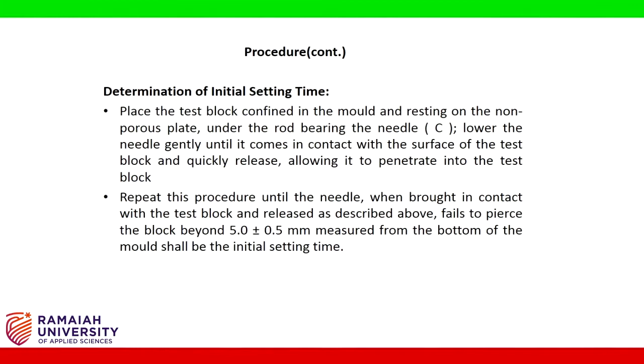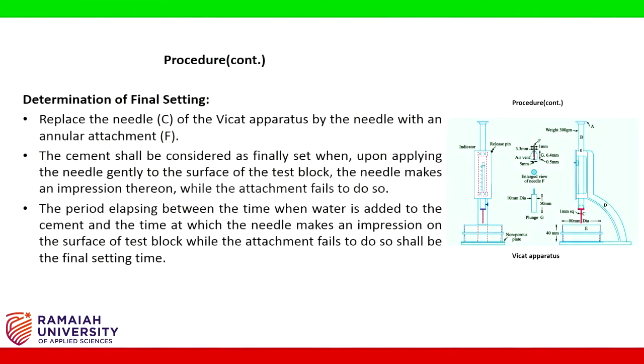Repeat this procedure until the needle, when brought in contact with the test block and released as described above, fails to pierce the block beyond 5 plus or minus 0.5 mm measured from the bottom of the mold. This shall be the initial setting time.